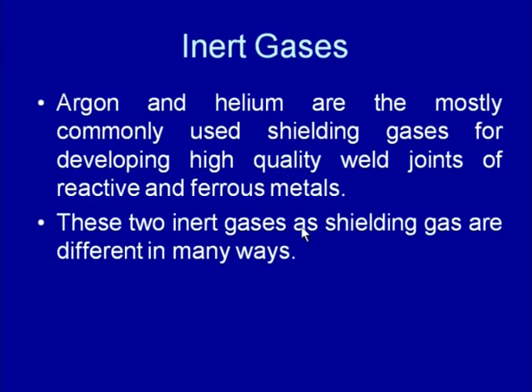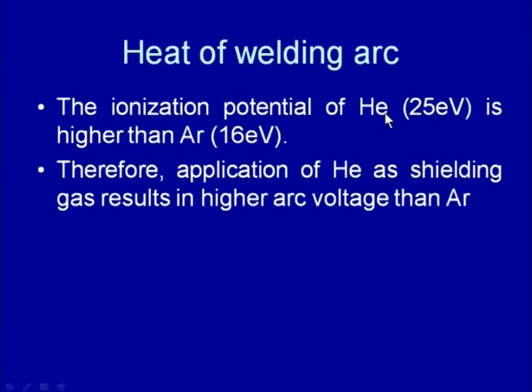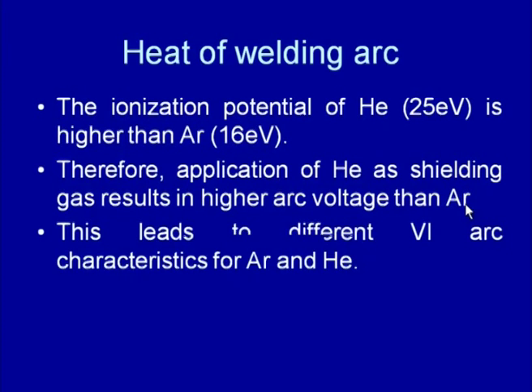These two inert gases as shielding gases play different kinds of roles under different conditions, and their characteristics are also found to be significantly different. If we see, the ionization potential of helium is found to be much higher than argon, and because of this, application of helium as a shielding gas results in a higher arc voltage than argon, and the higher arc voltage in turn leads to a different VI characteristic, where the VI curve is on the higher side than when argon is used.